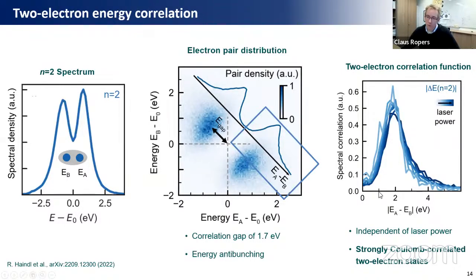Or it's not possible to emit 2 electrons within these 150 femtoseconds with an energy difference of less than 1 electron volt. And that's actually quite surprising. It does not correspond, I should be honest, to the numerical simulations which we've carried out. So this really suggests that there's a new type of 2-electron emission process, which has not been reported before, a 2-photon, 2-electron emission process, which directly leads to a strongly Coulomb-correlated 2, and in this other case, also 3 electron